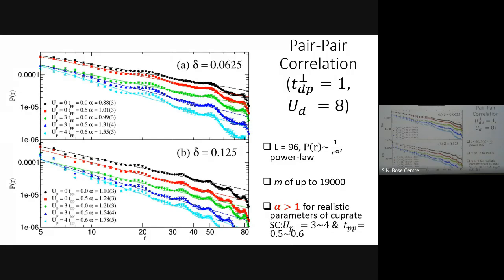This is just to show that we did a real calculation. Don't bother with this. We'll go to the next slide. So essentially, this is our unit. This is Imada's parameter set. When I say L equals 96, that is 96 times 5, because that's the number of orbitals. So 96 times 5 is quite large. That's the largest three-band model ever tried. So these are not small sizes.